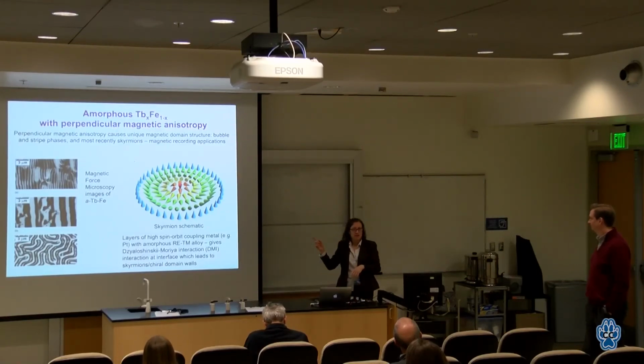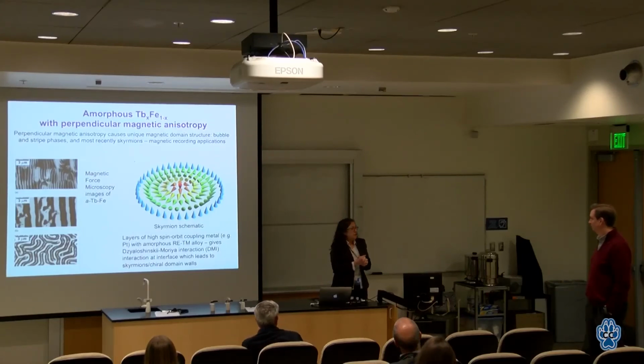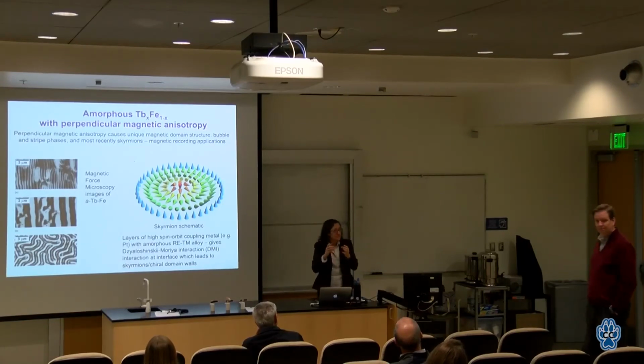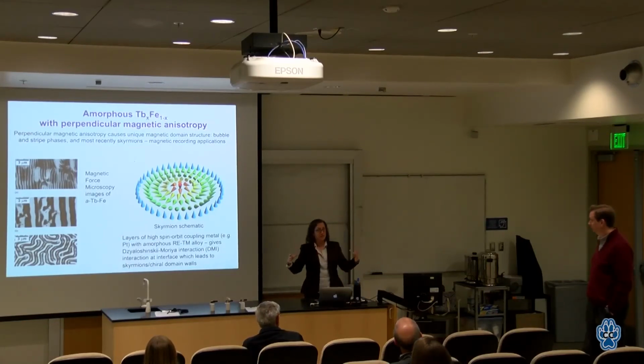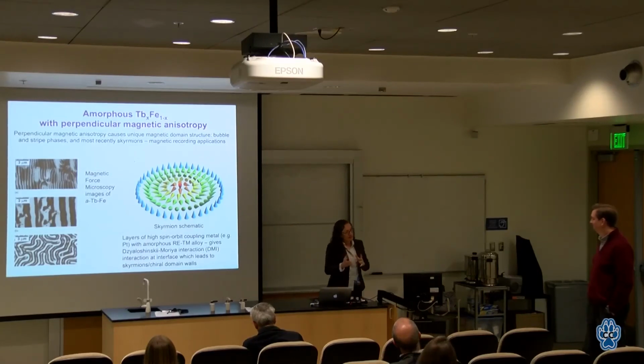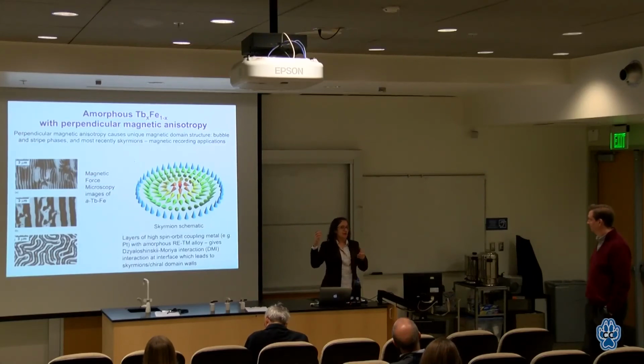So there are skyrmions that are tiny. There are literally skyrmions that are like 2 nanometers, 20 angstroms, just like 20 atoms across. So there are little tiny skyrmions, and then there are great big skyrmions. And in fact, anybody who has heard of the old-fashioned bubble memories, which were prevalent back in the 70s or 60s even, they're big. They're like a micron, and they can be skyrmions too. So the size greatly matters, because that has to do with how much they pin and whether you can move them.